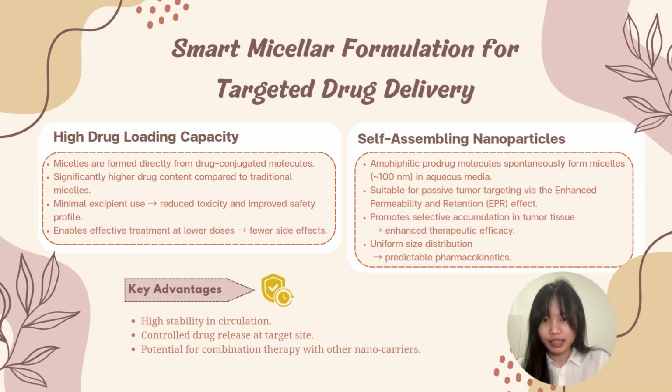These are self-assembly nanoparticles made from amphiphilic prodrug molecules that spontaneously form micelles of about 100 nanometers in size when placed in water. This size is ideal for passive tumor targeting through what is called the enhanced permeability and retention, or EPR effect. That means the micelles can selectively accumulate in tumor tissue, improving the therapeutic outcome.